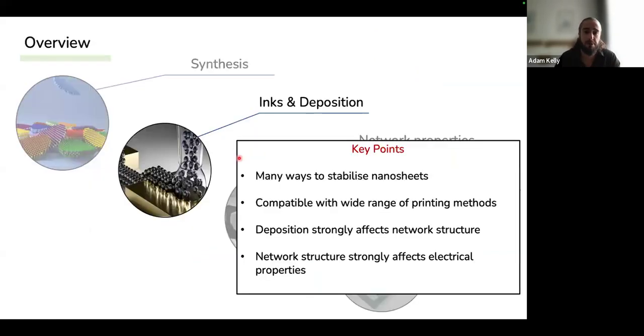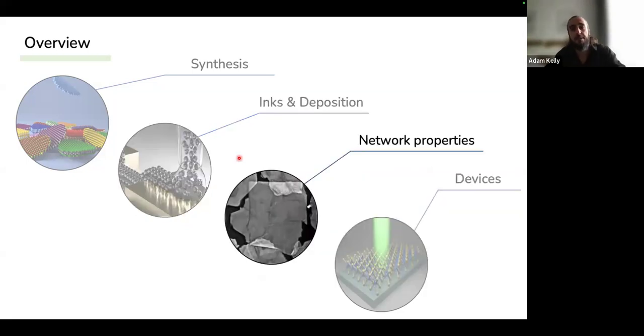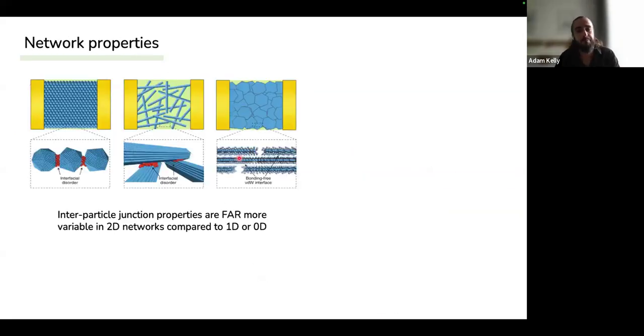So the key points when it comes to inks and deposition are we have many, many ways to stabilize our nanosheets, depending on what process you're trying to do. They are compatible with basically every printing method that we can think of. The deposition itself strongly affects the structure of the network. However, post-processing techniques can alleviate those effects. And what we see as well, which is important, is that the structure of the network strongly affects the electrical properties. So that takes me on to the network properties themselves.